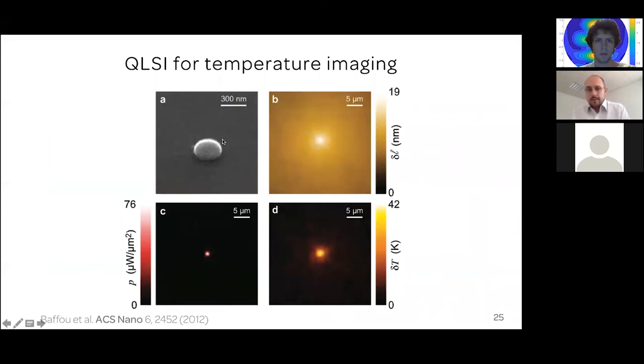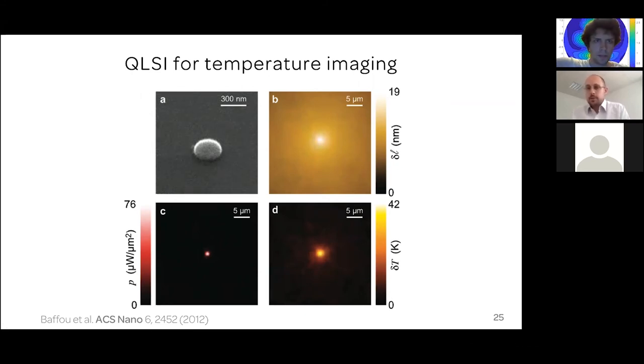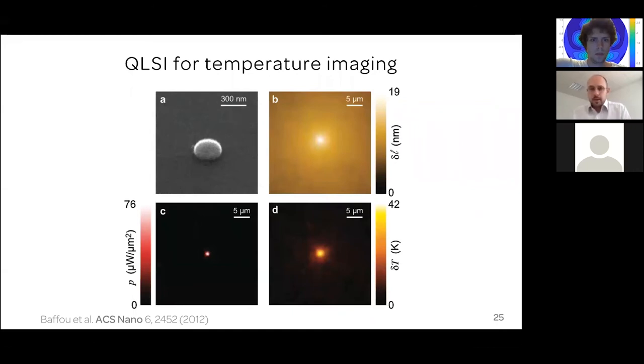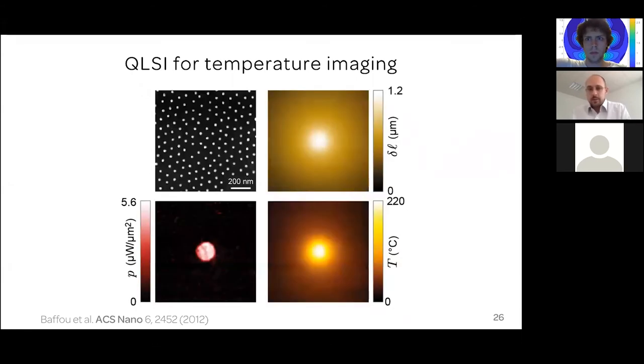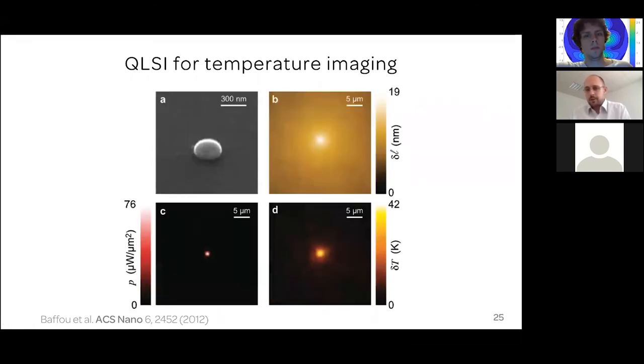Here is a phase or optical thickness image — in nanometers — of the wavefront distortion created by the temperature gradient when heating a single gold nanoparticle. This is not directly a temperature profile; it is a wavefront distortion due to a three-dimensional temperature profile. But using theory, we retrieve the three-dimensional temperature profile from this phase profile. We also retrieve the power per unit area — a unique quantity not measurable by any other microscopy technique. All other temperature microscopy techniques measure temperature but not this power density. By summing all pixels, you can even measure the total power delivered by the particle to its surroundings. This approach works not only for a single nanoparticle but for many nanoparticles simultaneously.